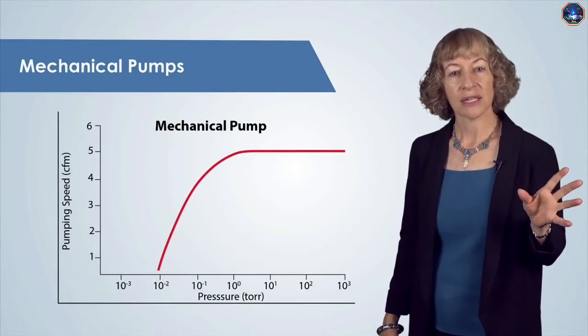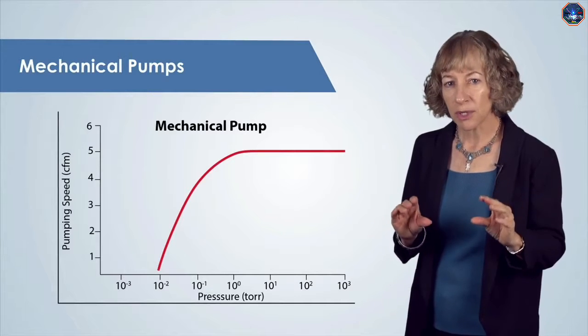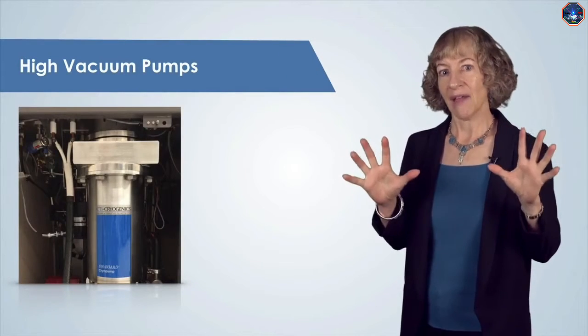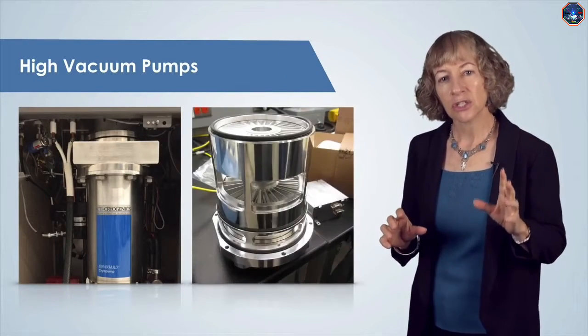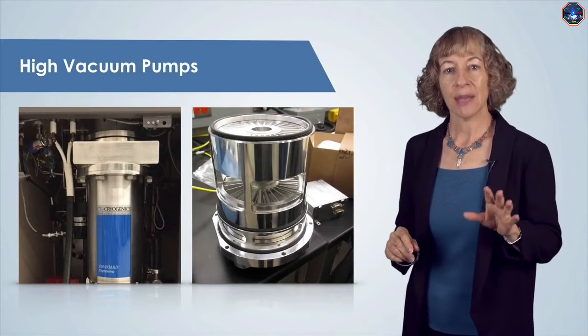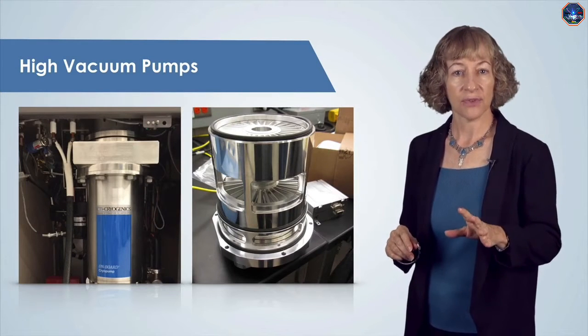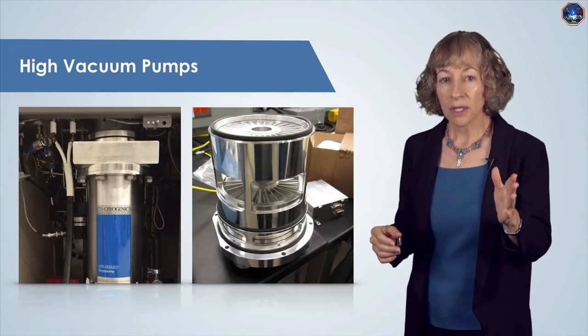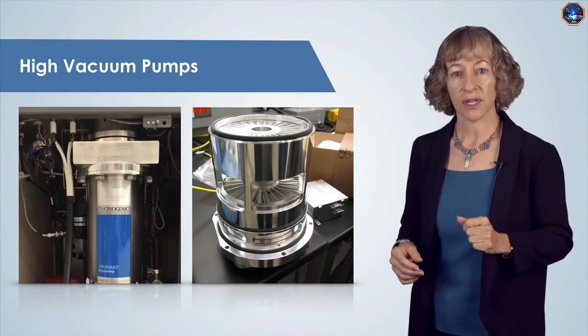Mechanical pumps alone cannot typically reach pressures low enough for thin film deposition of high quality, so we need to use another pump, a high vacuum pump, in addition to the mechanical pump for high purity deposited thin films, since air molecules in the vacuum chamber will introduce impurities in the film.